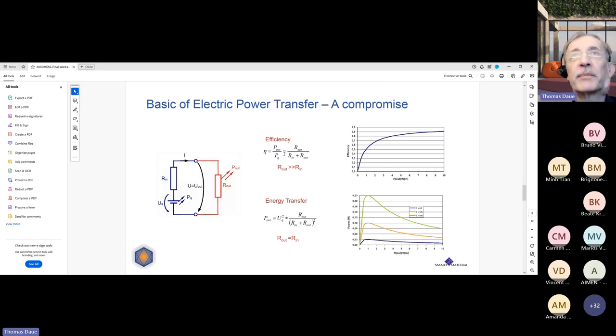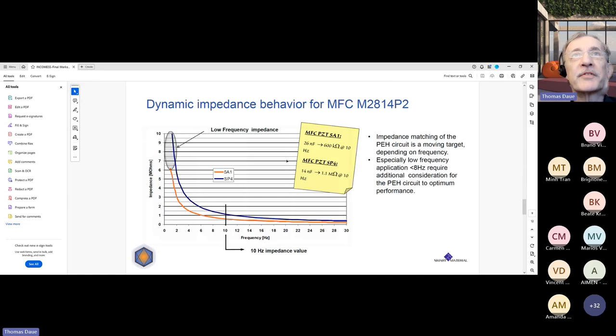Why is it so difficult with PZT? I'll just give you one example. This is the M2814P2 energy harvester MFC, and it changes its impedance with frequency. So for frequencies higher than 10 Hertz, you have an almost good or similar impedance. But if you move below 10 Hertz or 8 Hertz, as it is often with wearables or some other applications, it's exponentially higher than here. So here's your conundrum. Basically, your electronics have to adapt to those different impedances to increase the efficacy. So that's something very well to keep in mind.